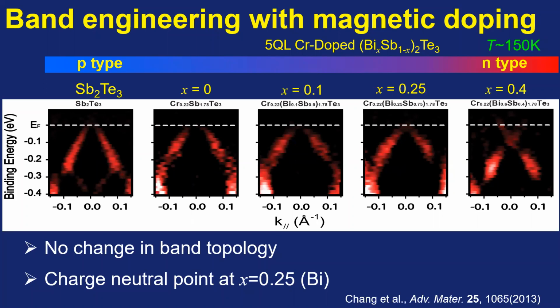And if we introduce some bismuth, the Dirac point approaches the chemical potential. At 40% doping, the Dirac point is below the chemical potential. So around x equals 0.25, the chemical potential is crossing the Dirac point. The reason we didn't see the magnetic exchange gap is because the measurement temperature is 150 Kelvin. So at this temperature, there is no ferromagnetic order.